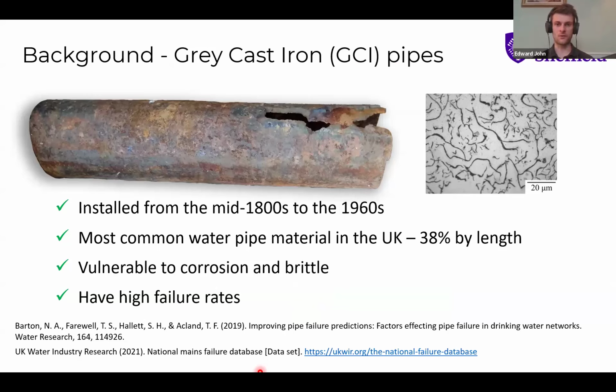Important things to understand about these pipes are that they are particularly vulnerable to corrosion and the formation of deep localized corrosion pits, and they're also very brittle, so they tend to crack rather than yield like a steel pipe might. One of the causes of both of these attributes is their graphitic microstructure. This image on the top right is at 100 times magnification, and it shows the very small flakes of graphite that you find within the microstructure of these pipes. These act like pre-cracks almost, and enable this brittle behavior. But we'll come back to the importance of those a little bit later on.